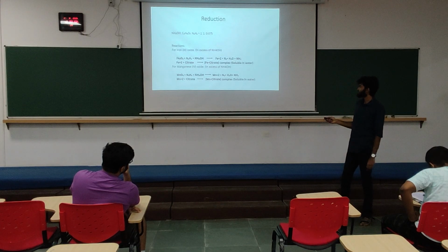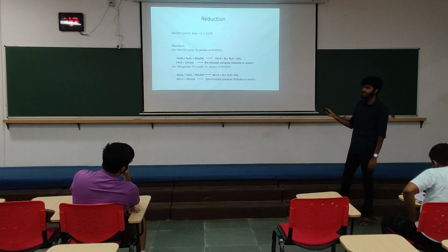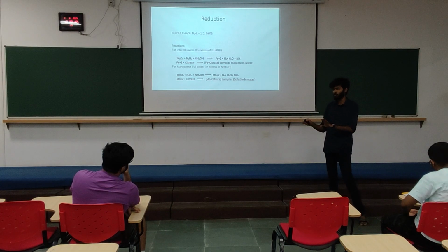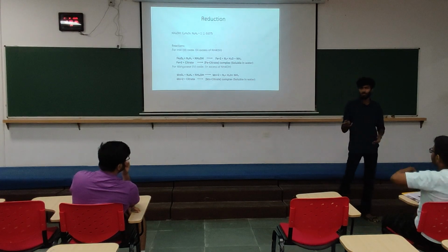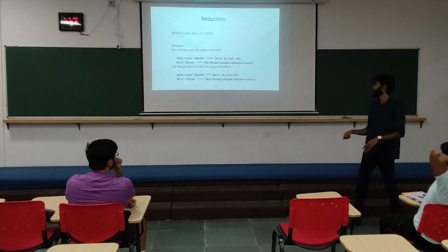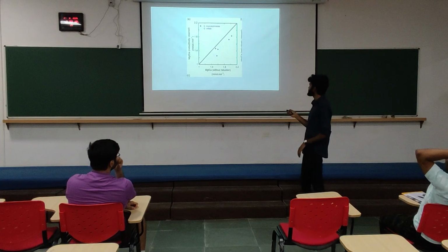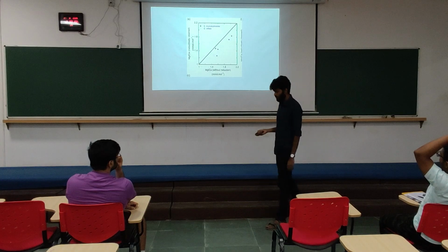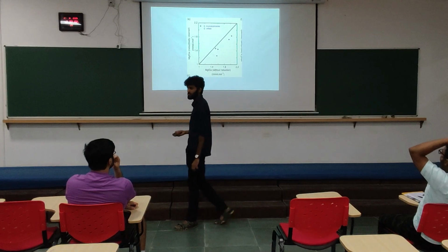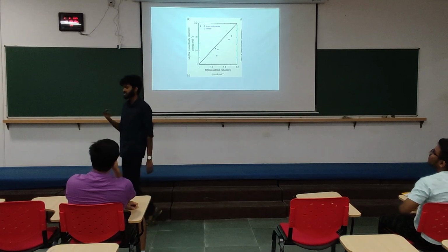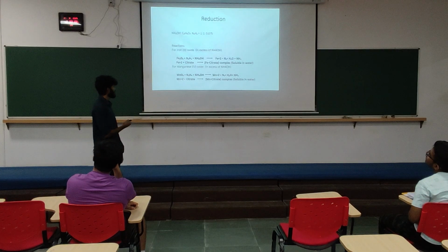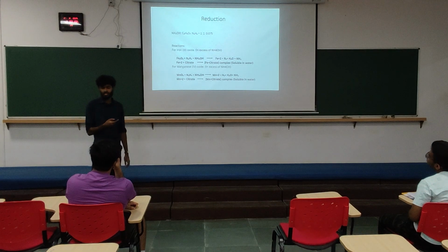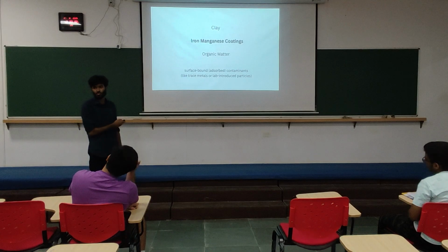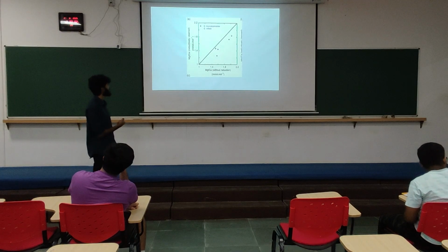So the problem with the reduction is that it dissolves the carbonate. We don't want the carbonate to dissolve. We don't want the magnesium ratio to come down. So that is the problem with the reduction step. We don't do the reduction step in every sample. We only do it in the samples where the FeMn contamination is too high. So we don't do this every time.